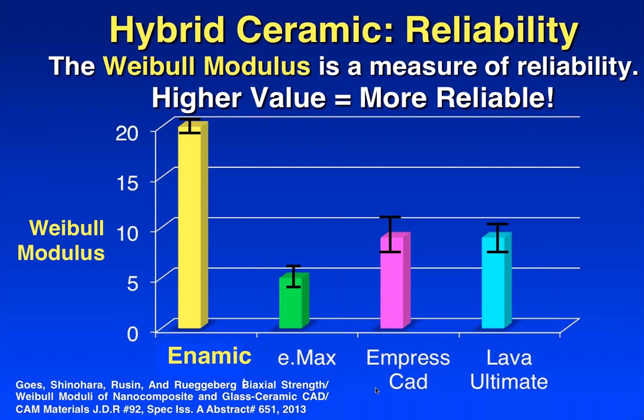So let's say we have a material that has a load-bearing capacity of 1,000. If we have a high Weibull modulus like 20, most of the restorations that we make out of that material will fail right around 1,000. Maybe it'll be 950, maybe it'll be 1,050. That's not going to be a big spread. If we have something with a low Weibull modulus, say under 5, it might fail at 1,000, it could fail at 500, could fail at 1,500, and there's going to be a very wide spread of values there. So you may be the unlucky person that gets the material that fails at 500, or maybe you're the lucky person that gets it to fail at 1,500, but there isn't a lot of reproducibility in that material.